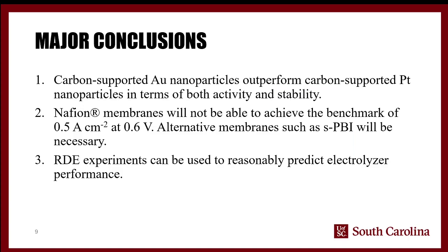So there are some major conclusions here. First, the carbon-supported gold nanoparticles clearly outperform the carbon-supported platinum nanoparticles that are traditionally used in terms of both activity and stability, which is great because gold is a little bit cheaper than platinum, and so that makes it of interest to us. Nafion membranes will not be able to achieve the benchmark of half an amp per square centimeter at 0.6 volts. The reason they can't do this is they cannot handle the high acid concentrations. I'll talk a little bit more about this in just a minute, but the short version is that the membrane resistance goes up exponentially as the acid concentration increases.